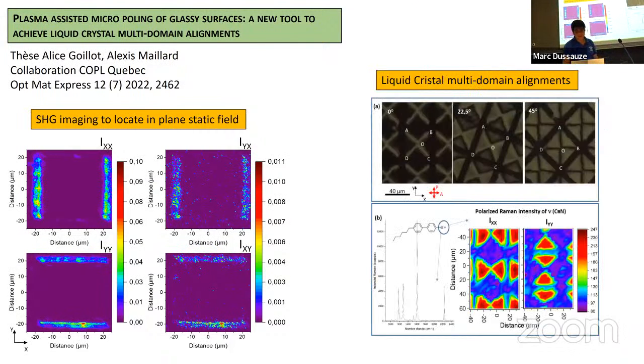Now you put the liquid crystal inside this, and you have a very nice multi-domain formation where all the liquid crystal will follow the electric field geometry that your treatment has induced on your glass surface. So, for example, here, this SHG signal proves that you have in these directions a field along the x-axis. And the liquid crystals here create this triangle domain, and they are oriented along this x-axis. So that's a very nice proof of concept that you can modify and add some electrical functionality on the glass surface, which will interact strongly with the molecular systems and induce their self-orientation.